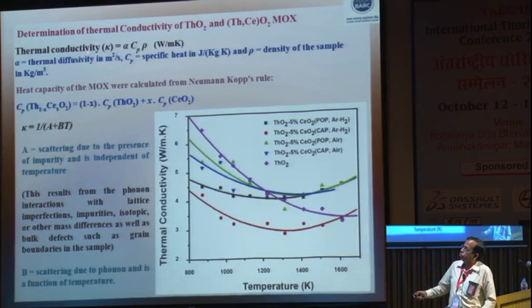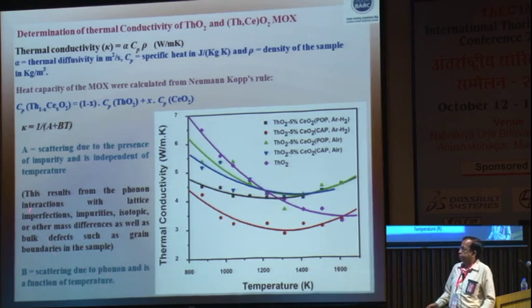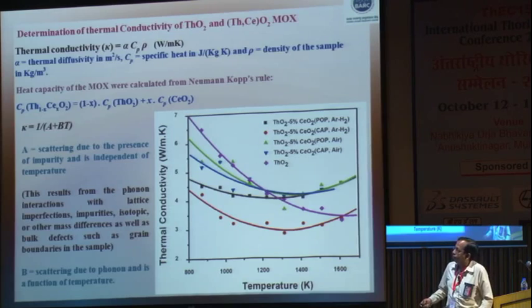The thermal conductivity is obtained from the thermal diffusivity, which was shown in the previous slide, and you need the specific heat data, which is evaluated from those of the pure components by the Neumann-Kopp rule, and this is the density. And if you put these two in place, you can get the thermal conductivity as a function of temperature. The thermal conductivity can also be expressed in this empirical form, 1/(A + BT), where A is scattering due to the presence of impurity and is independent of temperature, and B is scattering due to phonon and is a function of temperature. So, you can express thermal conductivity in this form also, with A and B parameters having different values. I will show that as well a little later.